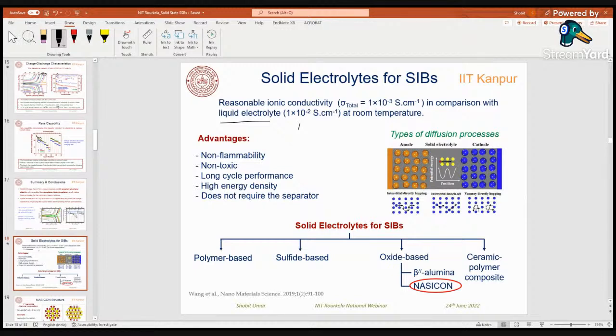Now comes the sulfide based electrolyte. Recently it has been reported that it can reach above 1 millisiemens per centimeter conductivity, right? So this is very promising. But the problem with sulfide based electrolytes is that they are very sensitive to the atmosphere, right? They can easily react with moisture, and then performance degradation will occur. So any type of fabrication that you have to do with the sulfide base, you have to do inside the glove box, inside the inert gas atmosphere. So that's a problem with the sulfide based electrolyte.